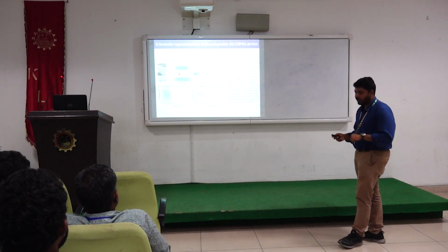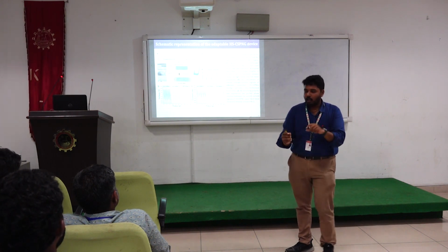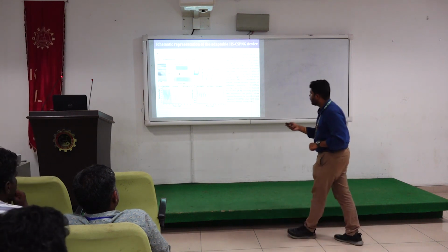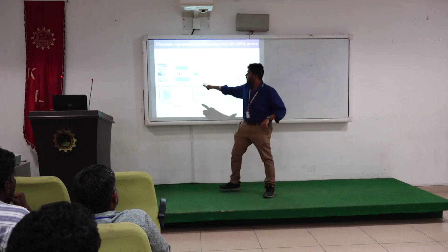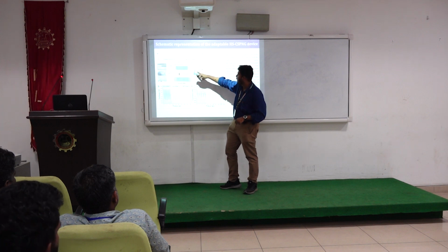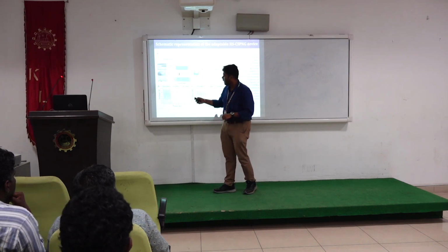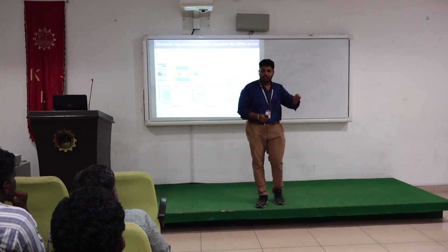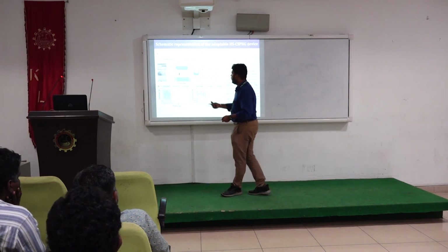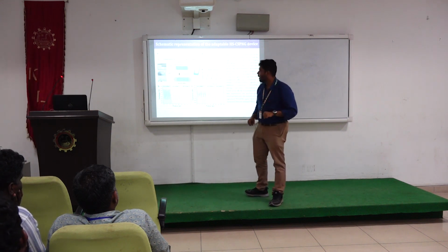For the second electrode, I bought a commercial adhesive bandage. On top of the bandage I put the strip. This is the composite strip. I attached it on the bandage here. You can see the bandage is there, and here I put the strip. I used silver paste as another electrode, which I coated. One electrode is titanium wire. The second electrode is silver.